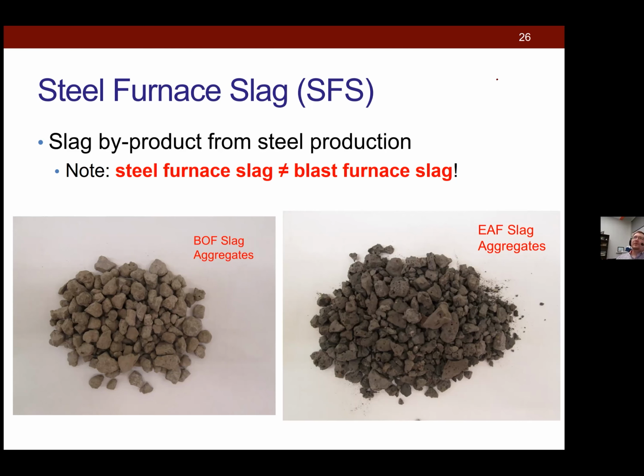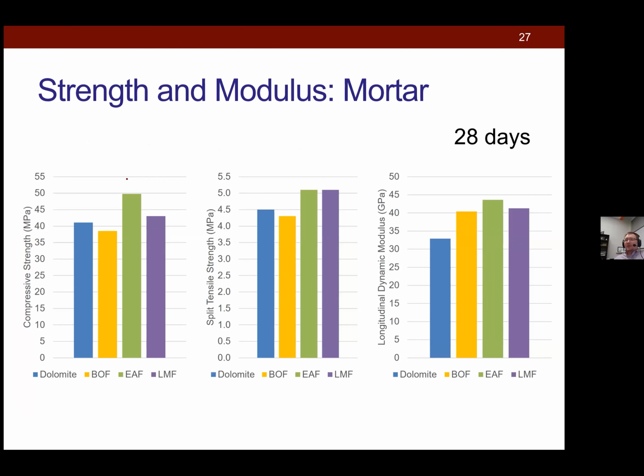Steel furnace slag is a byproduct from the electric arc furnace or the basic oxygen furnace. This is not cementitious. It actually can be quite expansive. It can contain a lot of free lime or free magnesia that expands when it reacts with water. But otherwise, it's a very hard, durable aggregate. It's mostly been overlooked because there were a lot of big failures in the US back in the 80s, so everyone basically said, forget it, we're not worrying about this stuff anymore. For the most part in the US, it's not really being used.